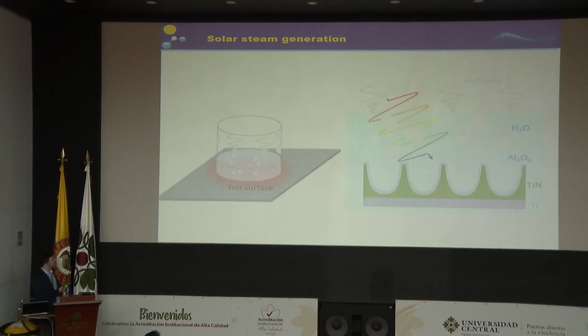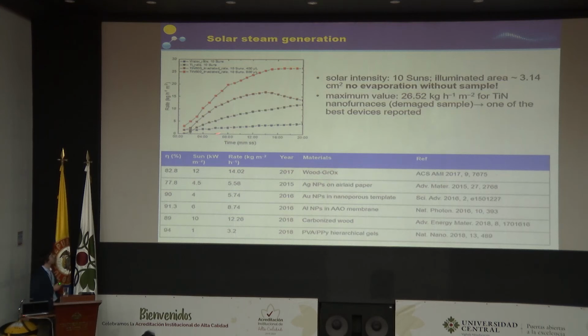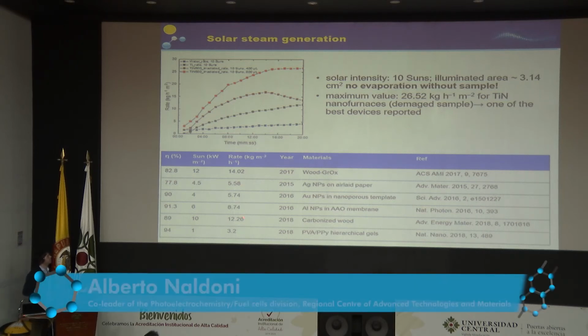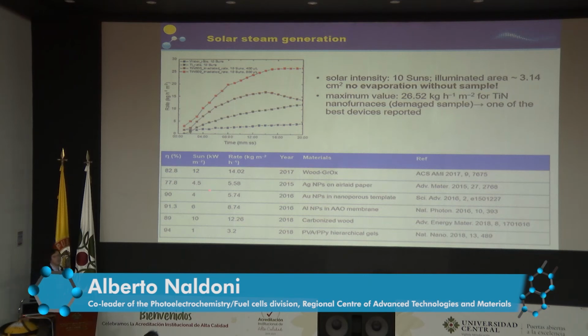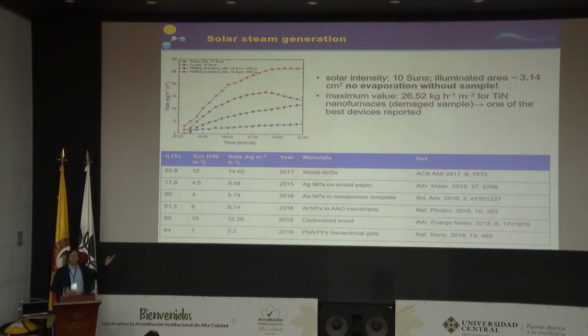What we did, and this is just preliminary, is use our nano furnace to evaporate water with concentrated sunlight. These are the reference values in the literature. The best materials can produce 14 kilograms per square meter per hour of water, which can be collected by normal condensation of the vapors. We gave it a try with our materials, and we achieved 26.5 kilograms per square meter per hour by using a damaged sample. So this is very promising. I'm confident that we can reach 40 kilograms per square meter per hour using just 10 suns, which can be achieved with a plastic Fresnel lens that costs $10, for example.